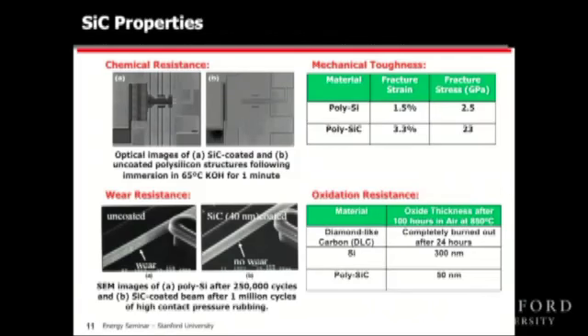So coming back to silicon carbide, with my collaborators at UC Berkeley, or the other side of the bay before coming here, I've done some tests on the material properties. For example, we've tested the chemical resistance of silicon carbide. This is a silicon-based device coated with a very, very thin coating of silicon carbide, 40 nanometers. If we expose it to hot potassium hydroxide, an uncoated device completely disappears. A device with a very, very thin coating stays intact. So we can ruggedize some of our devices with very, very thin coatings of silicon carbide. In addition, we subjected it to wear. This is an uncoated silicon device.